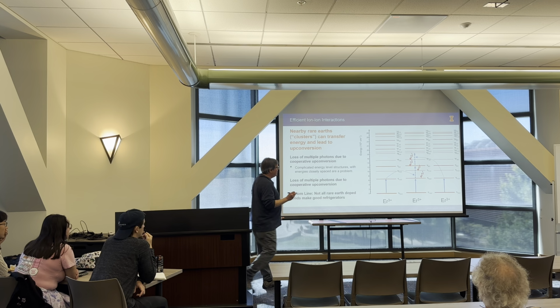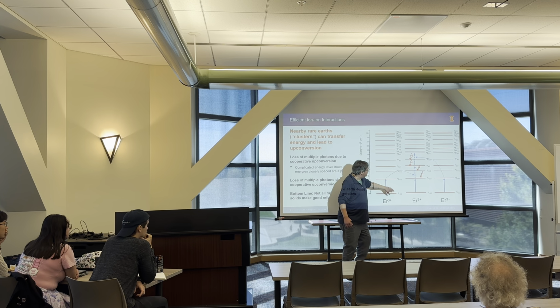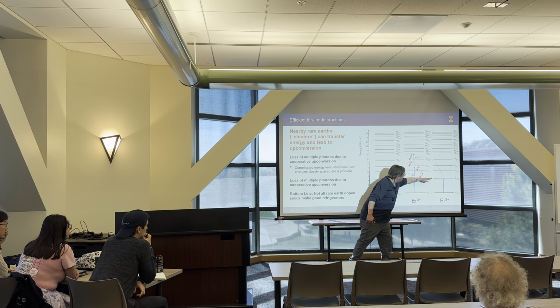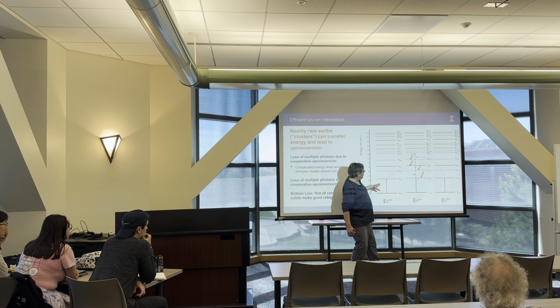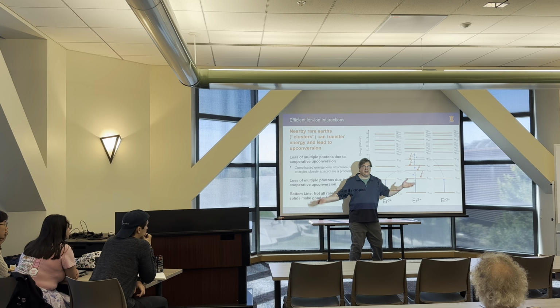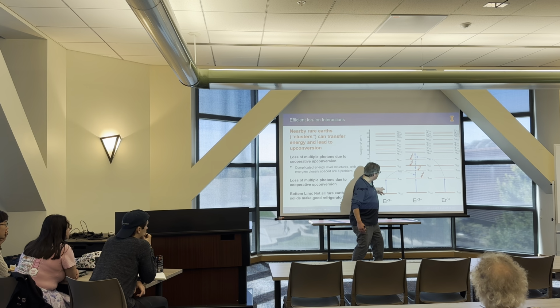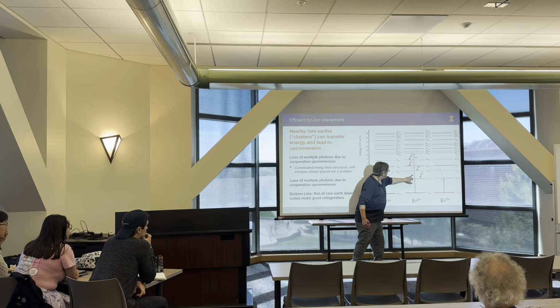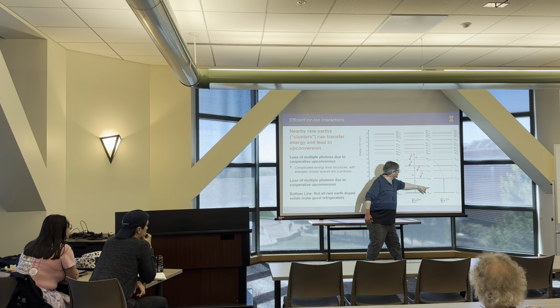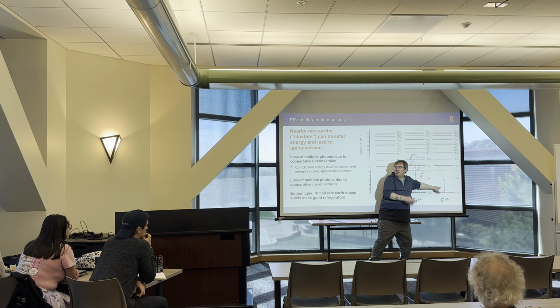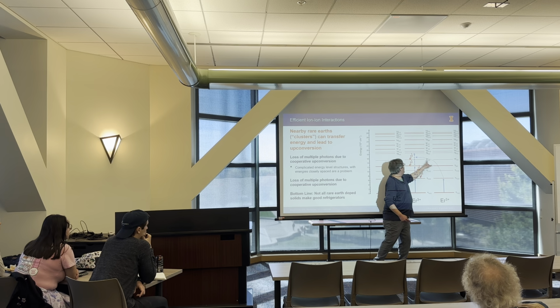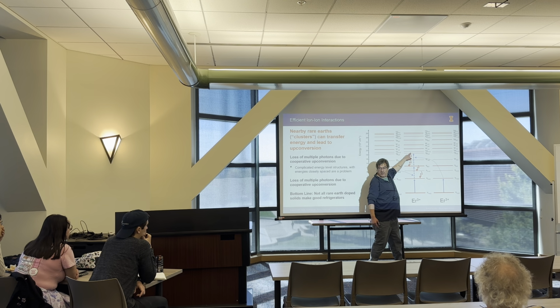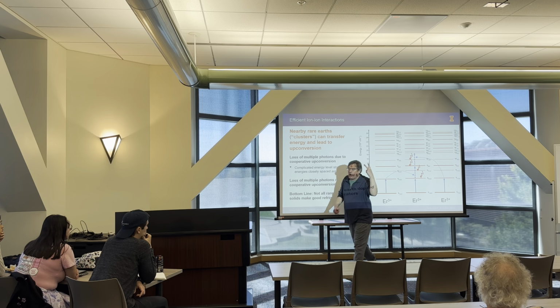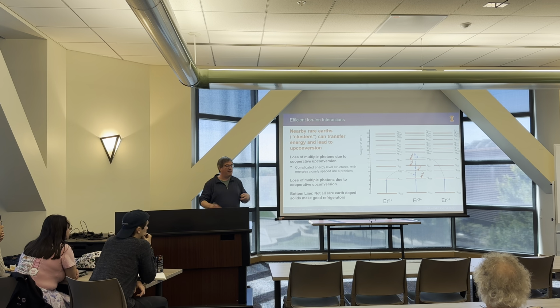So, for instance, let's say we have a cluster of three erbiums. Again, all three are excited, so they're up at this excited level up here. And then what can happen? Well, again, they play hot potato, and so this one wants to get rid of its energy, gives it to this one, comes up to here. This one says, oh yeah, you can take mine too, it's getting too hot in my hands. And then again, you get another upconversion effect, and then all of this trickles down the ladder to the original state, where you lost two photons in this process, to heat.